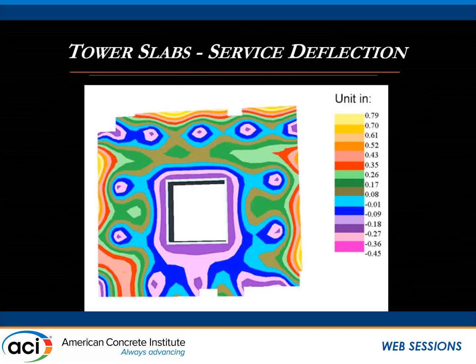Going on to the slab designs, it's a 7.5-inch slab, and what you see here is basically the serviceability deflection, the long-term deflection on that slab. As Cary mentioned, these dots right here are where the columns are, and we have a cantilever on this side, about 12-foot cantilevers on a 7.5-inch slab. This side right here is cantilevered quite a bit, and you have a little shorter cantilever on this side. The middle piece right here is basically the core, and on the outside you had a line load of curtain wall system coming down on the slab edge.